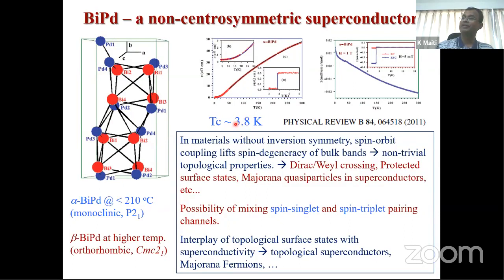And the crystal structure is such that if you are above 210 degrees centigrade, then it's an orthorhombic structure, but if you are at room temperature or below, then it has a monoclinic structure which doesn't have inversion symmetry in the crystal. So that means it's a non-centrosymmetric superconductor. This kind of material is very interesting because if you don't have inversion symmetry in the bulk, the spin orbit coupling will lift the spin degeneracy of the bulk bands.